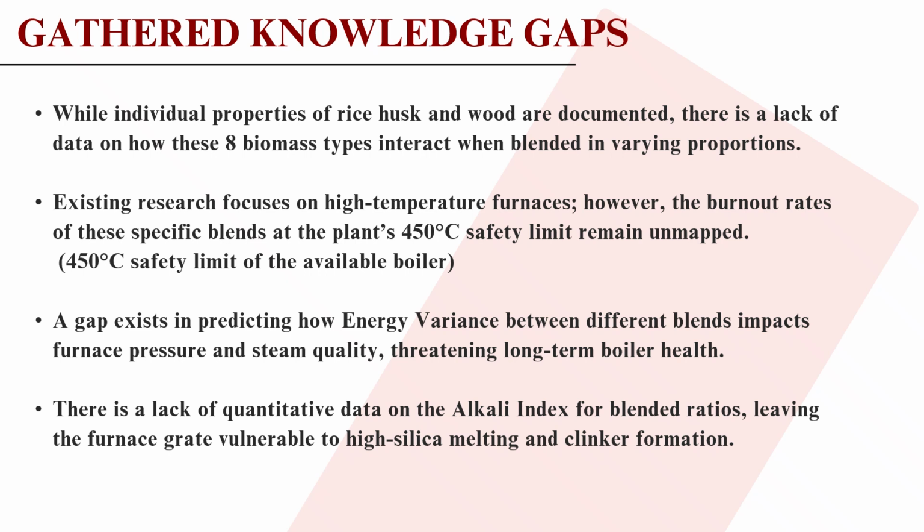Most research papers talk about very hot furnaces, but in our case, our boiler is limited to 450 Celsius. So we don't know yet which blend will stay lit and burn completely at this lower temperature without wasting fuel. And also there is a lack of quantitative data on the alkali index for blending ratios, leaving the furnace grate vulnerable to high silica melting and clinker formation.